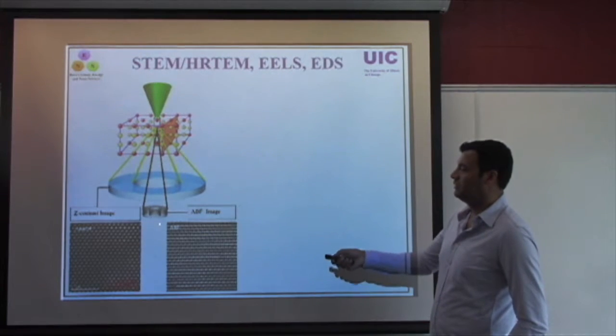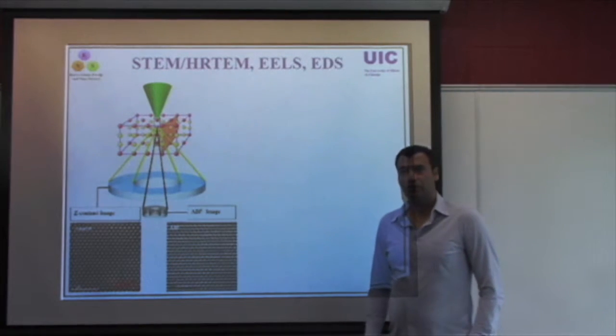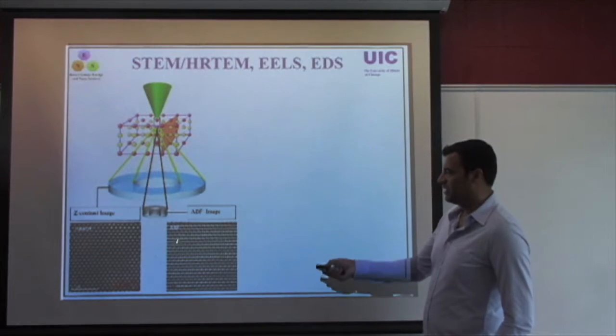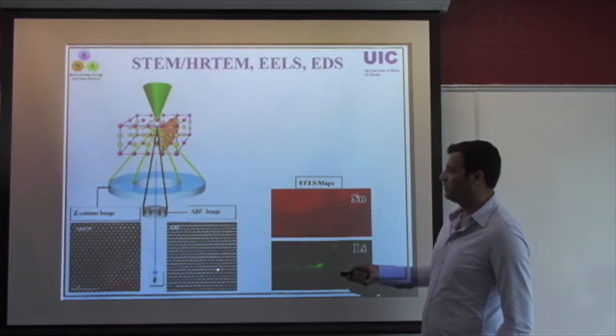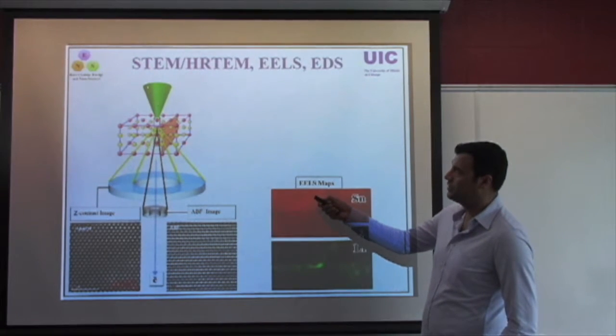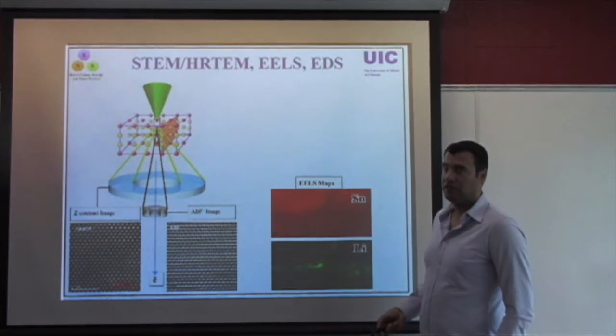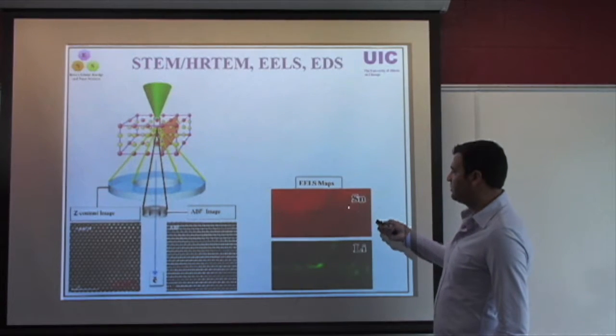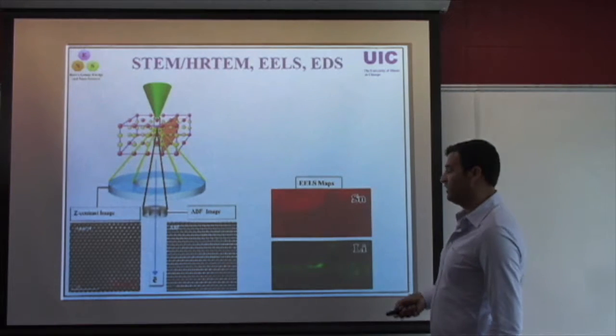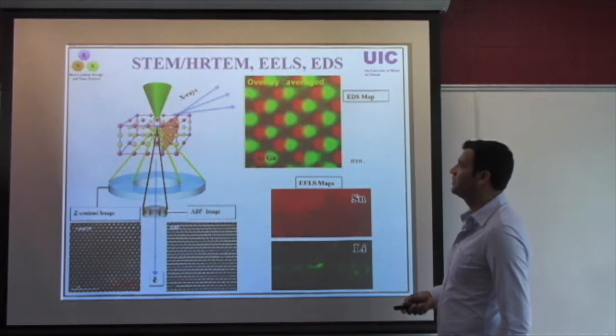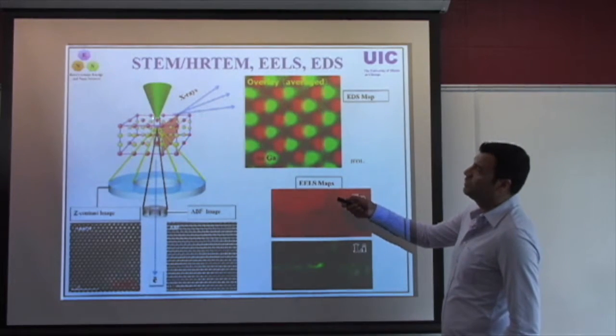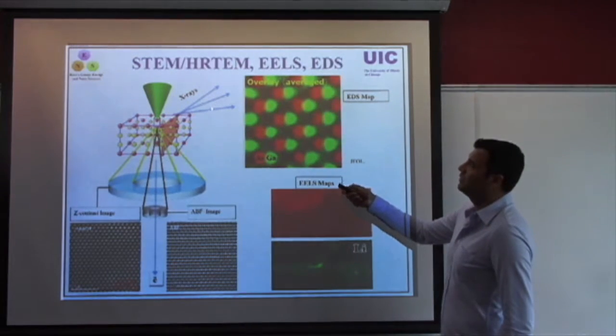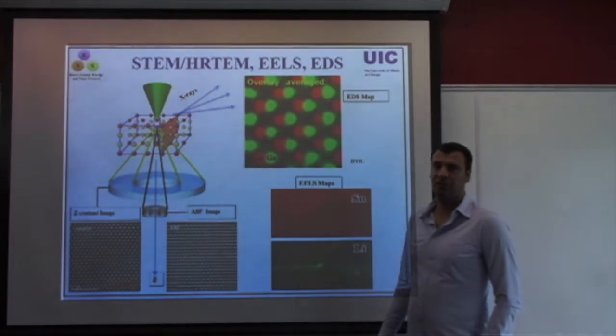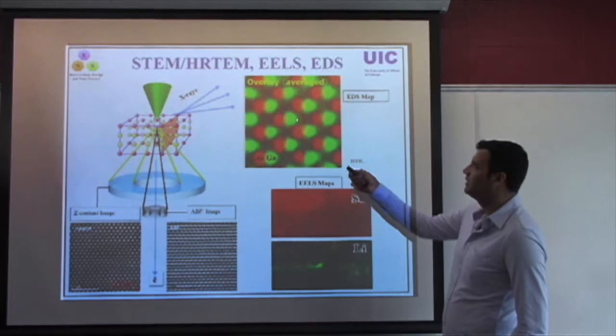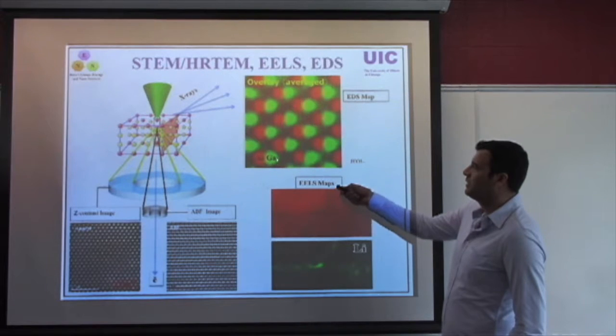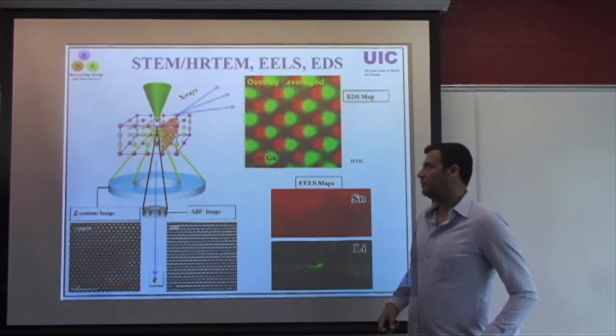And you can also have light element imaging. So in case, for example, you are trying to do sodium or lithium imaging, this capability is very useful for that application. This is an example where we are looking at how much energy the electrons lost by passing through the sample, and we call this EELS, or electron energy loss spectroscopy. Here we see a case where we are able to image directly the position of lithiums, and the quantification of that result. If you look into the X-rays that could be produced by interaction of the electron and the sample, then you can do X-ray analysis, and that's typically what we know as EDX or EDS maps of the sample here. This green and red indicates the position of gallium and arsenide within a sample.